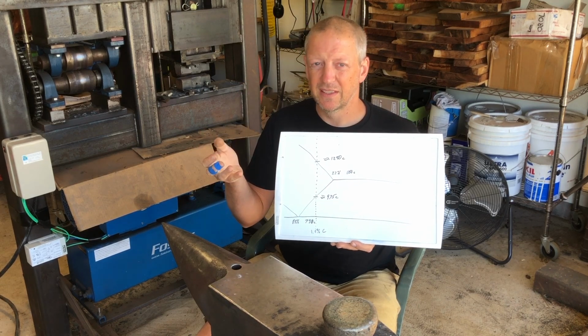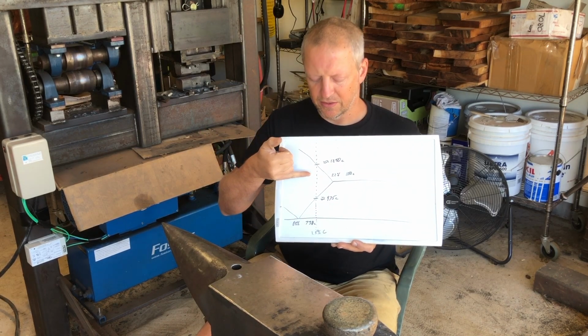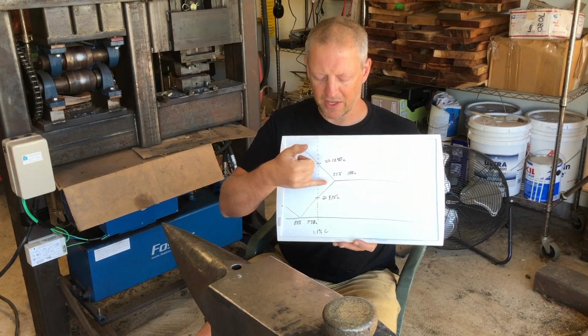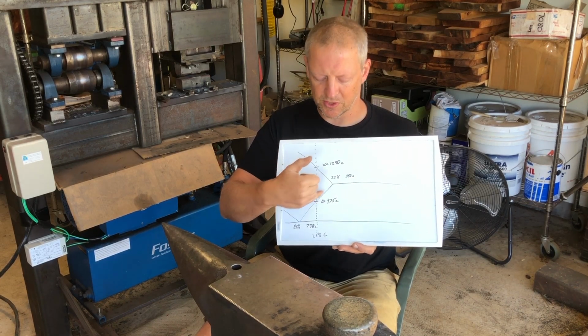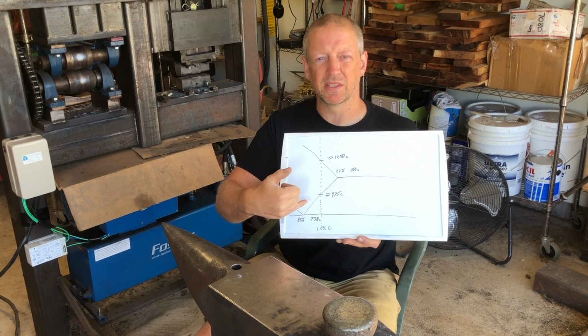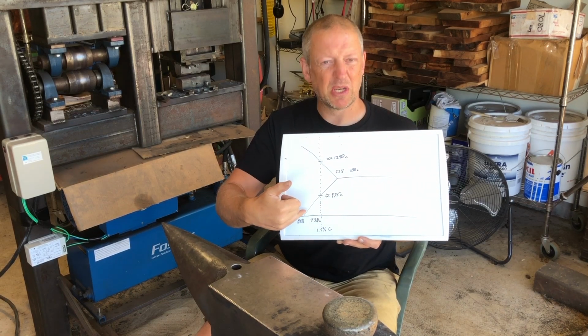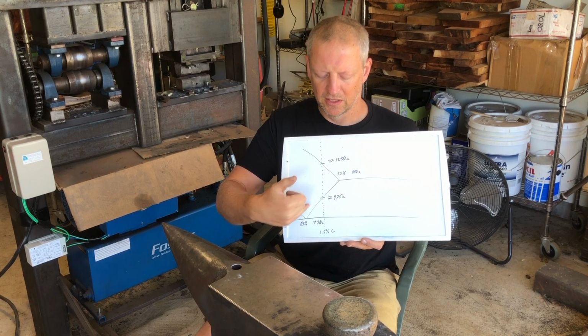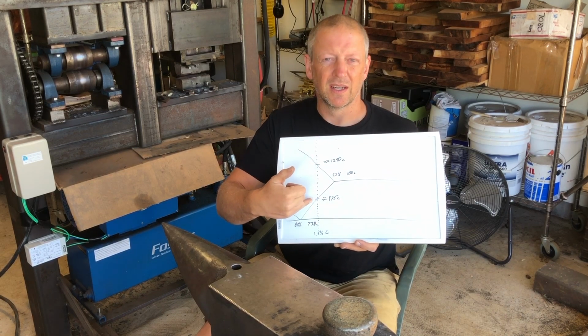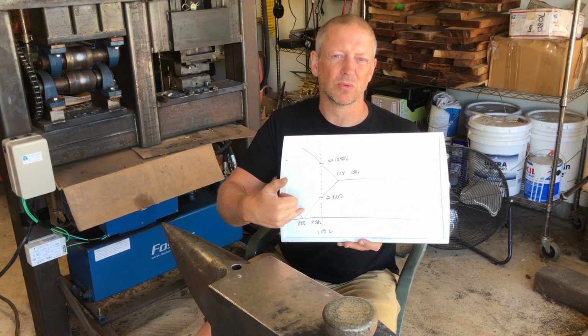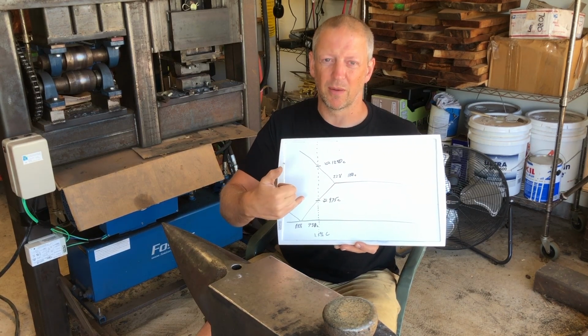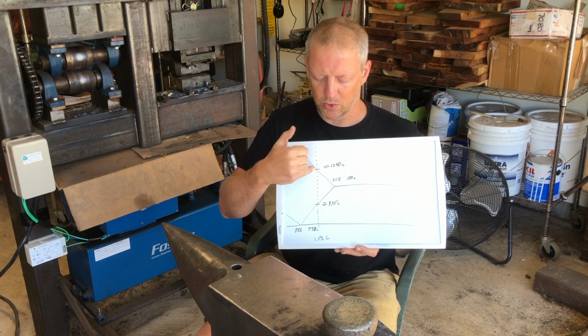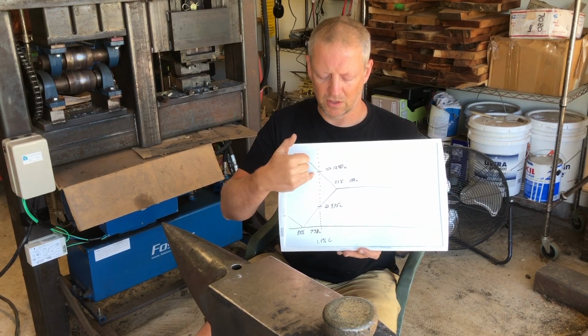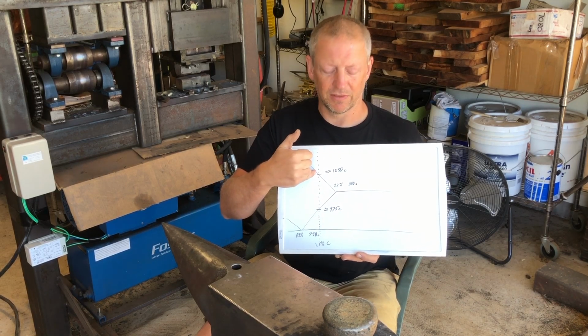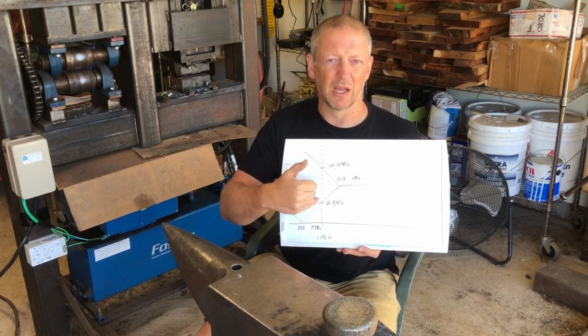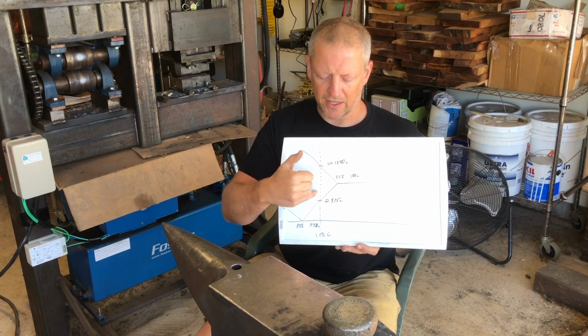But we have a lot of space here before we actually reach the temperature, because remember, this is what's called the ACM line, which basically means this is our cementite line or carbide line. This tells us where the steel really wants to start precipitating carbide. So as we're cooling through the austenite zone from full solidification down to the ACM line, during that entire period,